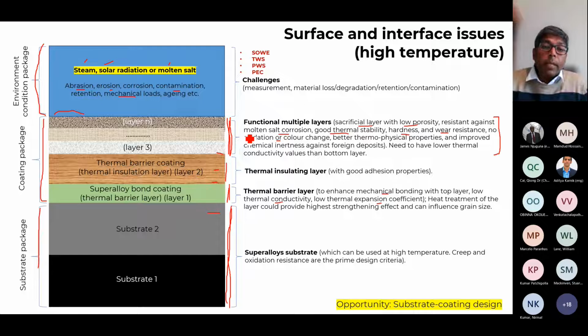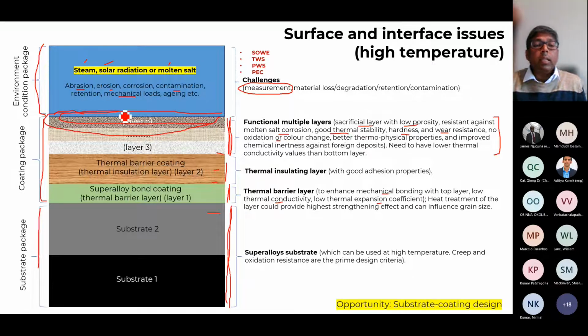And then once you have deposited it and you are using it in those electrolyzers, in situ measurement, I'm referring to, is not an easy task, because we would like to know the abrasion happening, the erosion happening, the corrosion rates. In all these cases, material loss is happening, or material is being deposited layer by layer, or contamination, thermal and mechanical degradation is happening. As you increase the duration, as I mentioned earlier, hours and days and weeks and months, you can have a sustainable design of the system. So we have to look into the details of these layers when we are manufacturing it.